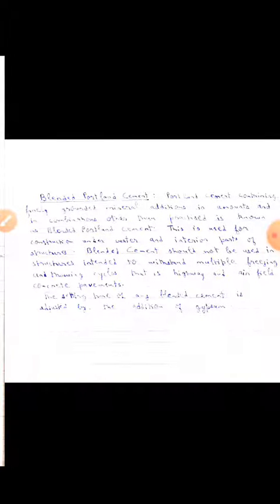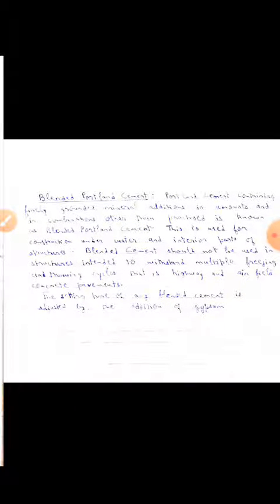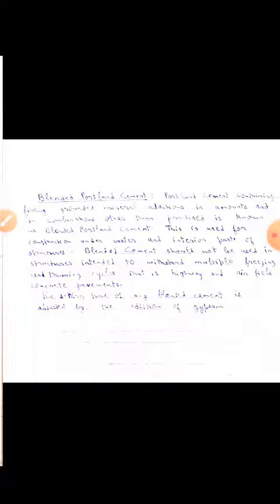The concrete of these parts of a structure is protected against the action of weathering agents such as drying, multiple freezing and thawing cycles. Since the forming texture of the hardening cement stones differ from that of Portland cement stone, the durability of concrete with the Portland pozzolanic cement as a binder is considerably less after multiple freezing and thawing cycles. It should also be noted that the frost resistance of concrete with the pozzolanic cement as binder, in which a fraction of hydraulic addition remains free and fails to be bonded with lime into calcium hydrosilicate, decreases considerably.